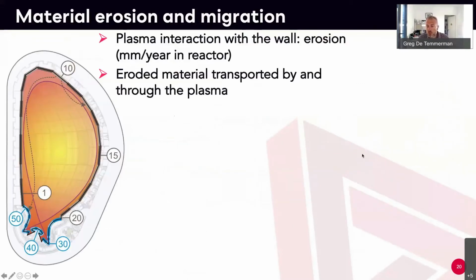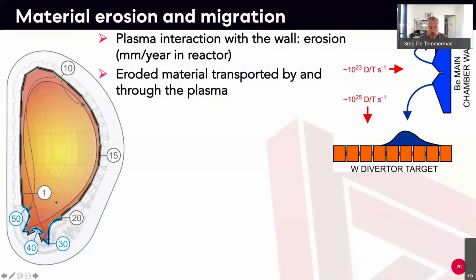Another thing which, okay, now you have the materials issues by themselves. So what happens in the bulk of the material? I said that particles are bombarding this material all the time. But what happens also is you're actually eroding the surface. So you're removing continuously atoms from your surfaces, so your material is thinning as a function of time.